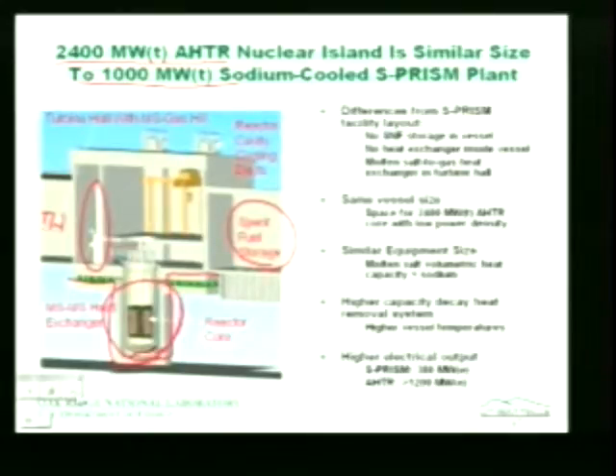The first important difference is that, in their case, they stored spent fuel in the vessel, and we moved the spent fuel out of the vessel and moved the heat exchangers out of the vessel. The second thing we did is we decided that our reactor would use the same size vessel as the S-Prism. We have a lower power density fuel, so we said if you've got a vessel this size at such a power density, how much power can you put in? It is 2,400 megawatts. The third is we have similar equipment size.